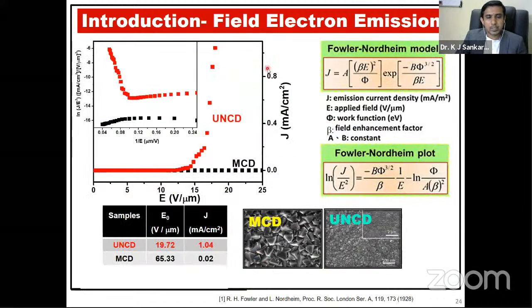So here I compared the field electron emission results of UNCD as well as MCD. The UNCD, as I have mentioned, is ultrananocrystalline diamond with a smooth surface and very small grains, and MCD is microcrystalline diamond with bigger grains of 5 micrometer size. Comparing UNCD and MCD, you can see that UNCD shows very good field electron emission, with the lowest turn-on field of 19.7. But MCD has a high turn-on field of 65. So it has a very high turn-on field.